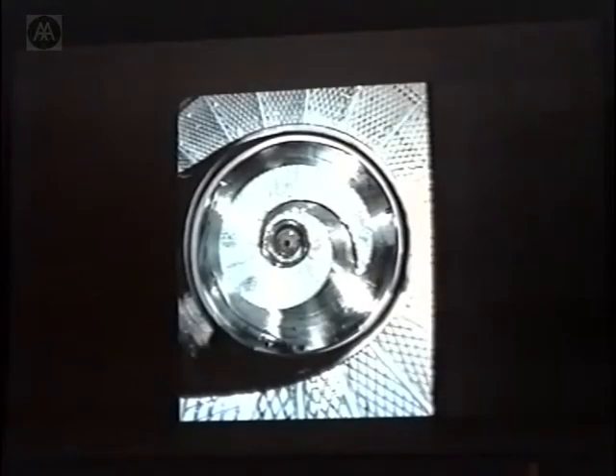This is one in a private house, and you can see, is there one of those little red pointers? You can see we had to build a little glass upstand on the back of the tread to comply with the staircase rule of no gap greater than 4 inches, for babies' heads getting stuck in the thing. But it can still be, as you see, very transparent, and you hardly even notice that. And that was the central tube, which was actually cut out of a steel tube to give the support to the inside of the treads, which were very, very simply just bolted down through a hole in the annealed glass. You can put holes in annealed glass, by the way.